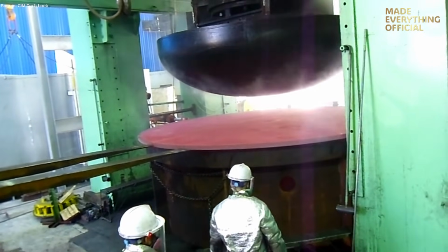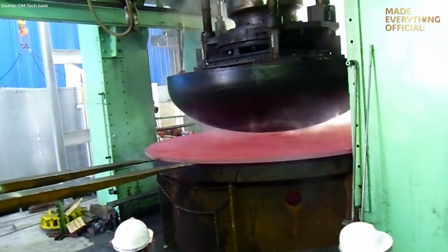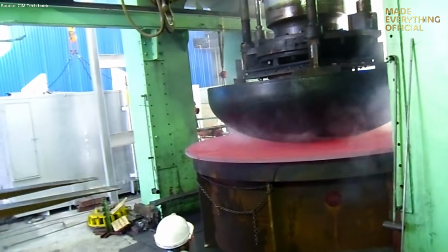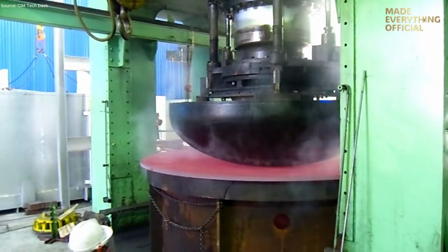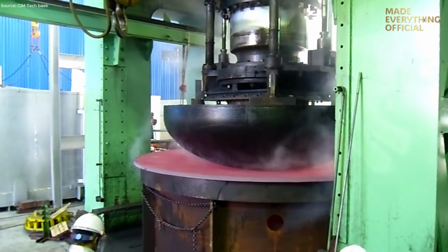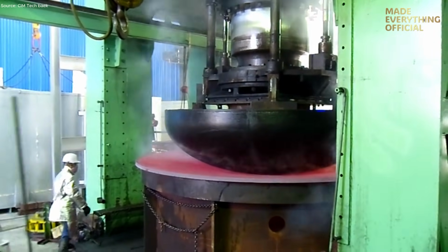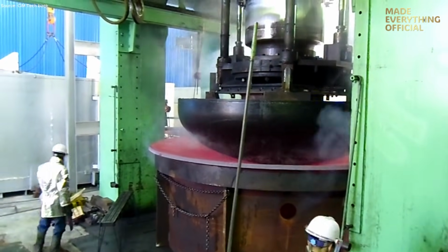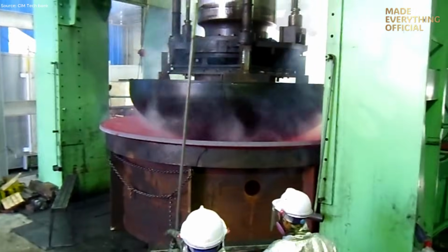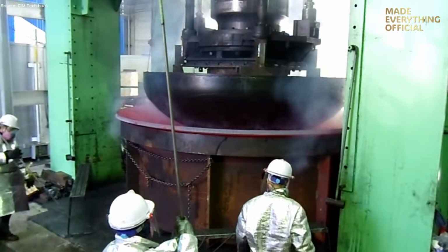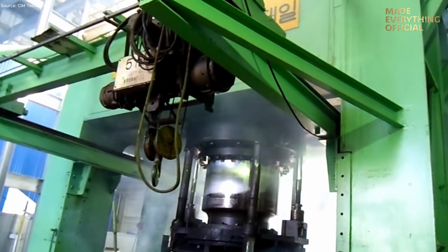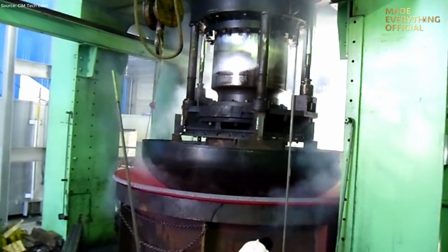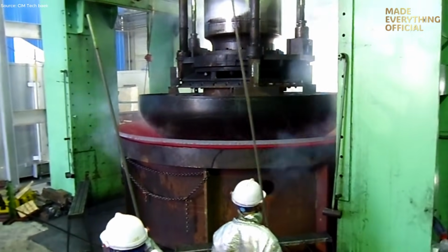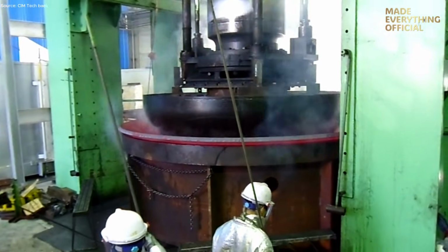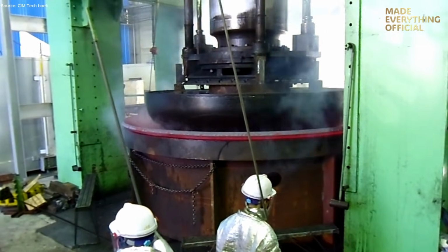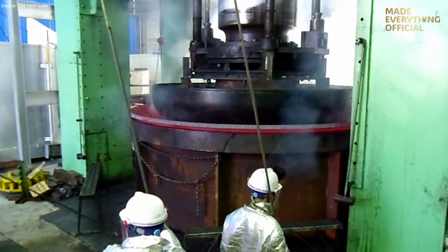The 3,000-ton press then applies controlled force to the heated blank, pressing it into a matched die set that defines the final shape of the tank or dish head. Because the material is hot, it flows more easily and fills the die cavity completely, producing smooth contours and accurate geometry critical for pressure-bearing applications. During forming, sensors and controls monitor press force and temperature to ensure consistent results across each cycle. Proper heat and load control prevent defects such as thinning, warping, or incomplete fills, which could compromise strength.